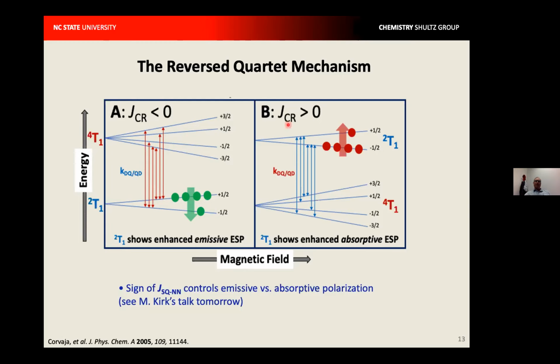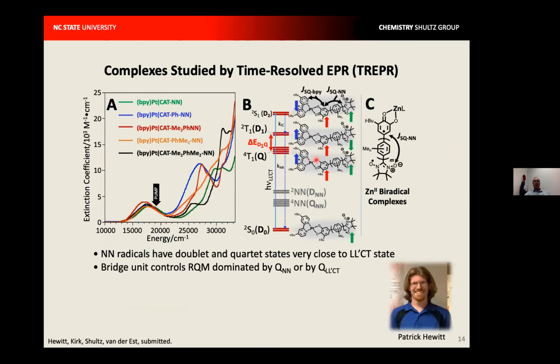The flip side of the coin is that when the chromophore radical exchange is ferromagnetic, then the trip-doublet lies above the trip-quartet, and you get a non-Boltzmann population of the lower M sub S level of the trip-doublet, and that would give rise to an enhanced emissive signal in the time-resolved EPR. Again, for our complexes, the trip-doublet is very short-lived, decays non-radiatively to the ground state, and the spin polarization is transferred to the molecular ground state.